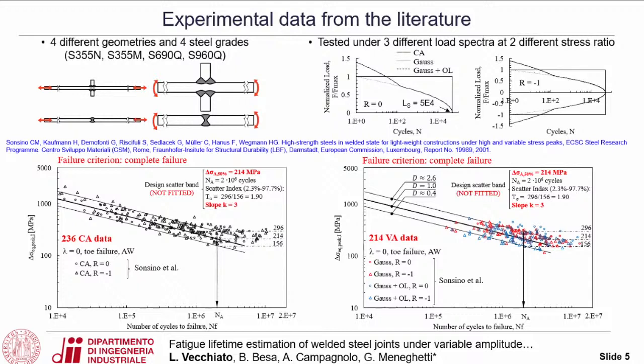In this work, they tested many different welded specimens. In particular, they were made of 4 different geometries, made of 4 different steel grades. And all these specimens were tested under 3 different load spectra, in particular, constant amplitude loading, Gaussian standard load spectrum, and also Gaussian with the overload spectrum, both at fully pulsating loading and fully reversing loading. So at the load ratio R equal to 0 or R equal to -1.